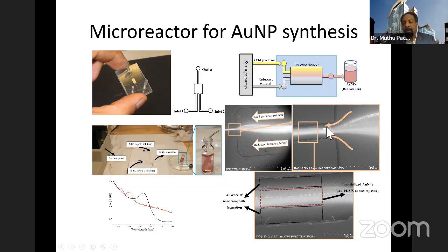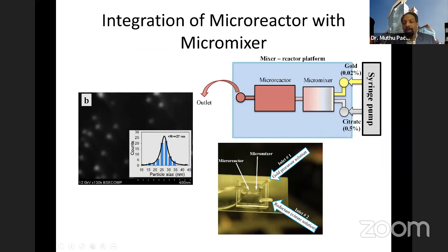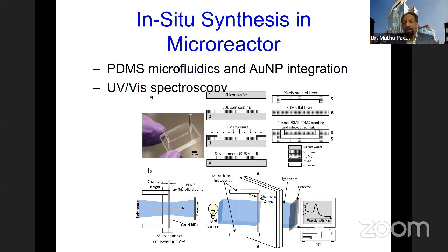Of course, if you want to make the nanoparticles more uniform, then we need to come up with some sort of 3D mixing. So we have a 3D mixer. I'm not going to go into it. We have made a 3D mixer so we can have a very uniform mixture of this precursor and reducing agent inside this microfluidic chip to get a better, uniform distribution of size of these nanoparticles.